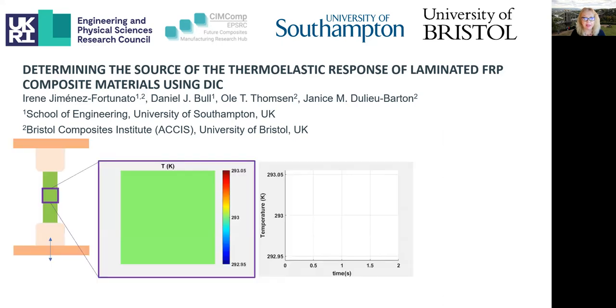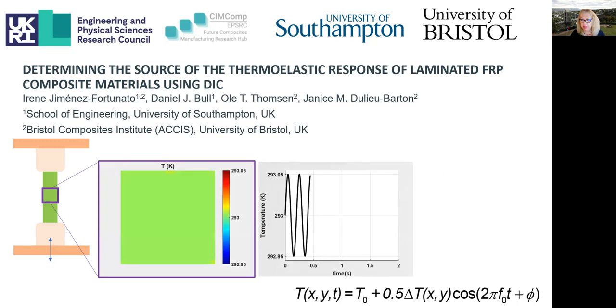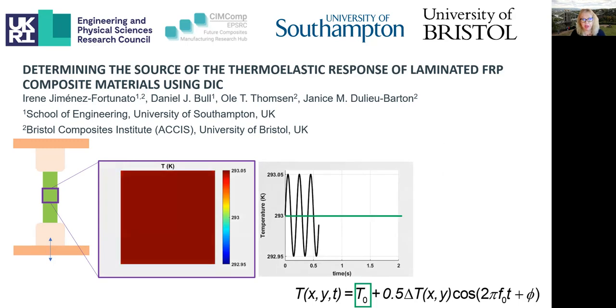In thermoelastic stress analysis, an infrared camera is used to capture images from a cyclically loaded object. Usually this object is loaded sinusoidally and this means that we can fit a function to determine T0, the mean temperature.